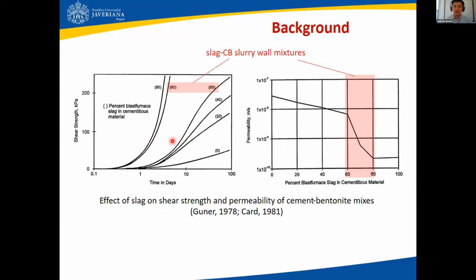And as far as properties, and to close this background, of course, shear strength and permeability are affected by the slag content. This granulated ground blast furnace slag is used as a replacement or partial replacement cementitious material in very large proportions, typically from 60 to 80% replacement within the cementitious component in slag-CB mixtures. So you can see here that there are typically important changes and increases in strength, or at least accelerated strength, if you will, and also significant changes in hydraulic conductivity due to the presence of an important amount of slag within the cementing component of the mixture.